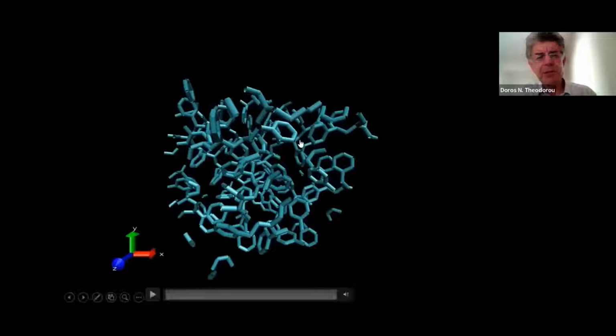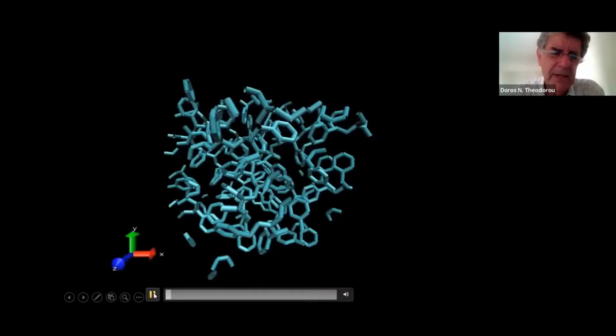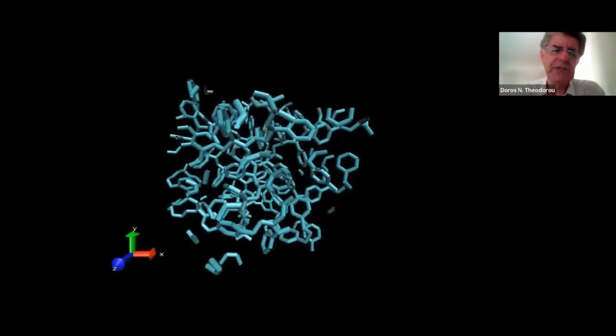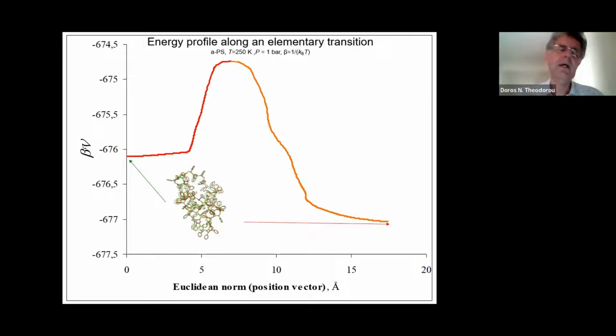This is one elementary transition to give you a feel of what this is about. This is, again, polystyrene, a rather small box of polystyrene, as you see. This is a minimum. The system is in a minimum of its potential energy, and we can have a transition going over a saddle point into an adjacent minimum. And you see that there is a very subtle rearrangement that changes many things in the system and goes from one minimum to the other. And this is the energy profile of this transition. We started at a minimum, we ended up at a different minimum, and we go over a saddle point. And here we represent the Euclidean norm of how much we have moved in configuration space. So the saddle point appears as a maximum. Once one has this energy profile, one can calculate the rate constants, as we know, for example, for chemical reactions.